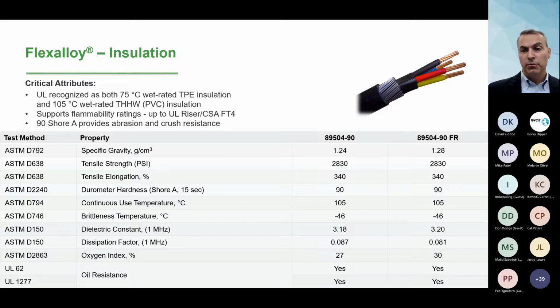They offer oil 1 and oil 2 resistance. They are VW1 rated, which is a small scale flame test. And the 90FR version additionally is 720 hour UV rated as an insulation. They are also UL recognized to 75 degrees C as thermoplastic elastomer wet location compounds at a minimum thickness of 31 mils or 0.78 millimeters. And with the relatively high hardness of 90 Shore A, it provides good abrasion and crush resistance. And since they're PVC-based elastomers, they are able to be recognized as both PVCs and TPEs.